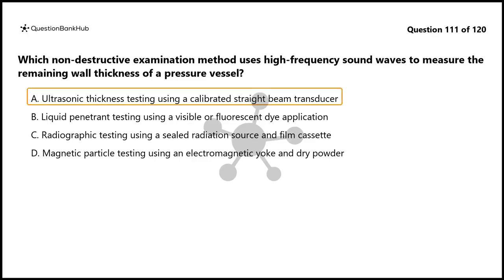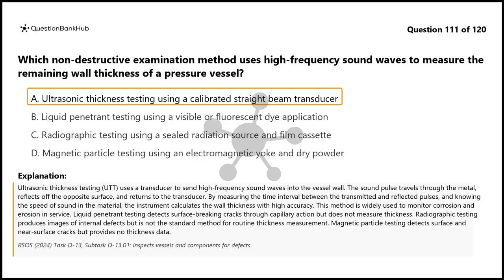The correct answer is A. Ultrasonic thickness testing, UTT, uses a transducer to send high-frequency sound waves into the vessel wall. The sound pulse travels through the metal, reflects off the opposite surface, and returns to the transducer. By measuring the time interval between the transmitted and reflected pulses, and knowing the speed of sound in the material, the instrument calculates the wall thickness with high accuracy. This method is widely used to monitor corrosion and erosion in service.